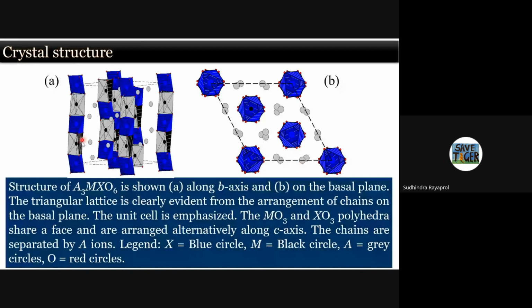This is along the AB plane, and this is the structure which you see from the top. If you see, you have these different chains which are placed along, this is the top view we are seeing. They have different unit cells, so you have different chains at the edges, and you have chains in between also. If you see carefully, this forms a rhombohedral unit cell actually, but if you take all these chains together, this forms a hexagonal lattice.